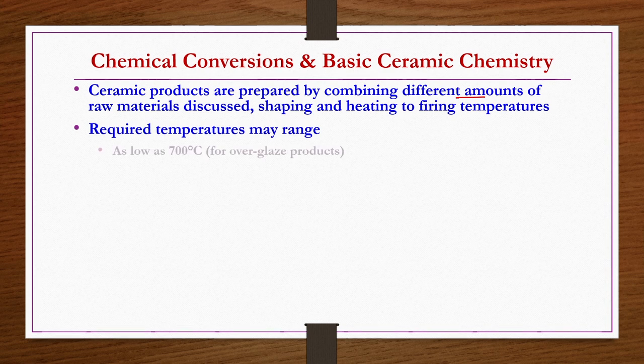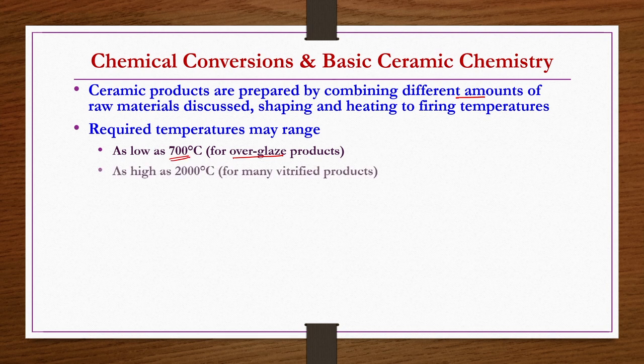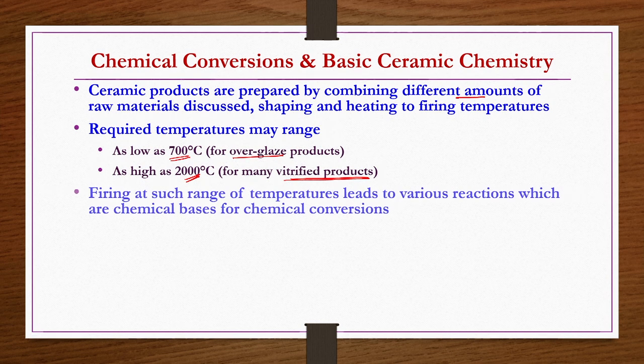requirement. Let us say if you wanted to have an over-glazed product, then the required temperature may be as low as 700 degrees centigrade only. But if you wanted to have vitrified products like glass products or vitrified ceramic products, then the temperature would be as high as 2000 degrees centigrade. Firing at such a range of temperatures leads to various reactions, which are the chemical bases for chemical conversions, right?